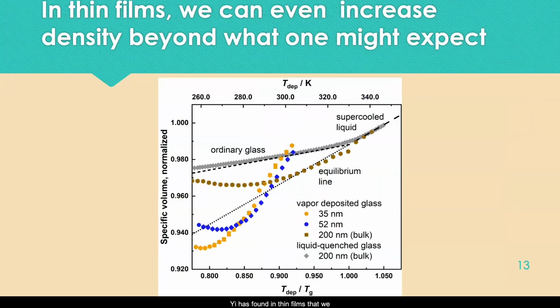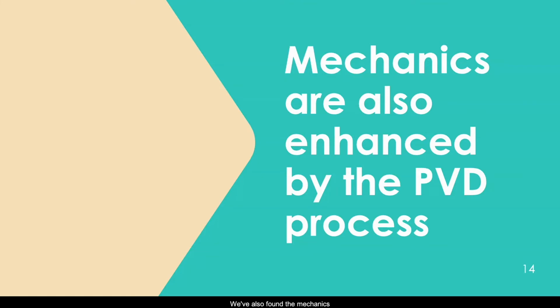Yi has found in thin films that we can increase density beyond what one might expect based on the supercooled liquid line alone. So you might think that the supercooled liquid line forms a kind of limit of how much we can increase the density. He's gone beyond that in particularly thin films. We've also found that mechanics are enhanced by the PVD process.